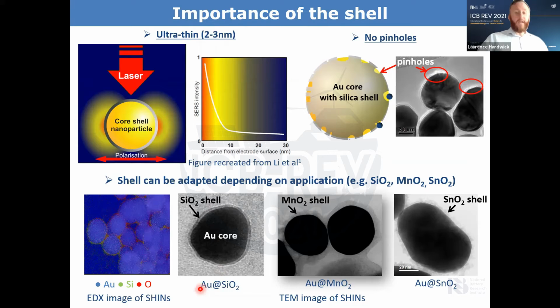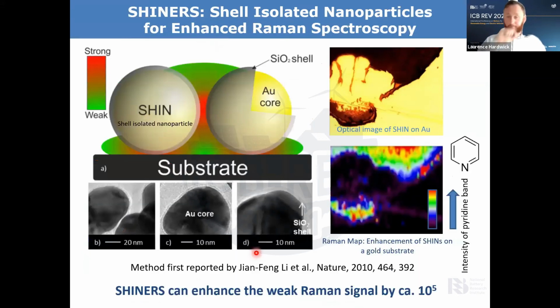Here we have a transmission electron microscopy image of a SHINERS particle, a shell isolated nanoparticle. We have our gold core, and this is about 50 nanometer diameter, and we have a 2 to 3 nanometer uniform silica shell that's been grown onto these particles. And this just highlights the power of the spectroscopy.